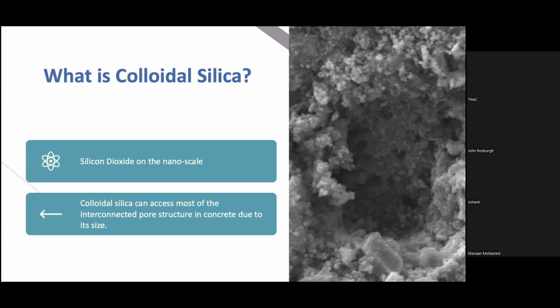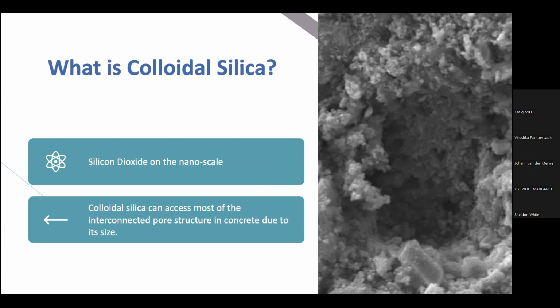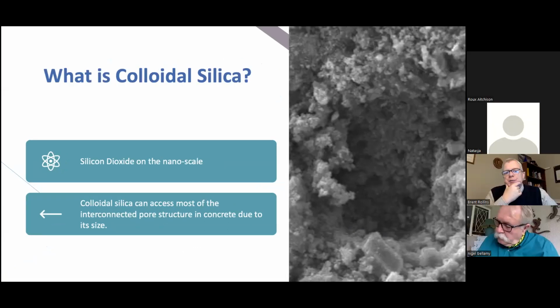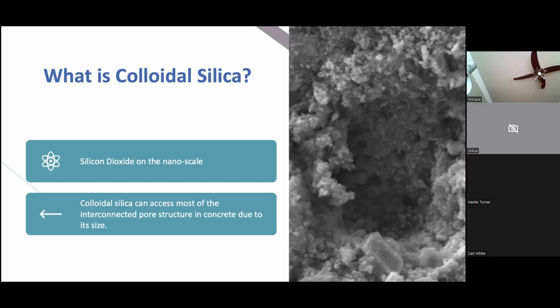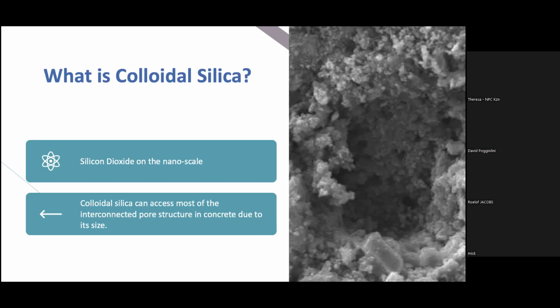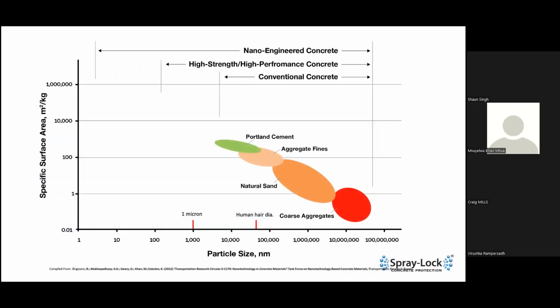So a colloid is just a suspension, right? To simplify it, if we assume that this concrete pore that you see in the picture is as deep as it is wide, 20 microns, then that small, third of a human hair diameter size pore would hold about 700,000 average size colloidal silica particles. So the small size of colloidal silica is important for two reasons. Number one, that means that the colloidal silica can reach almost all of the interconnected pore space in concrete. Number two, it means that it has a tremendous amount of surface area.